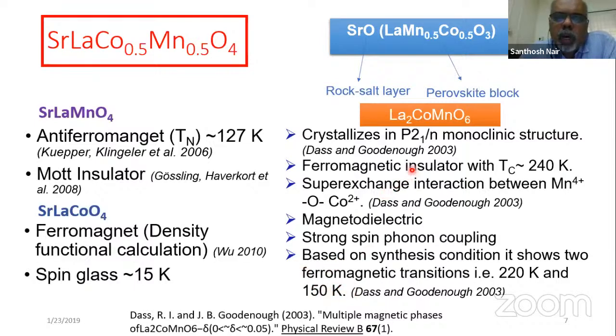Now, what happens if you make it layered? Essentially, you introduce a strontium oxide layer in between the perovskite blocks. The perovskite block is the ferromagnetic layer, and you increase the distance between the ferromagnetic blocks by incorporating a strontium oxide layer. If you do that, you are weakening the magnetic interaction along the z-axis, and what do you get? I will take this as a parent compound and want to see what happens to the magnetism if you reduce the interaction along the z-axis, but the XY plane interactions remain intact.